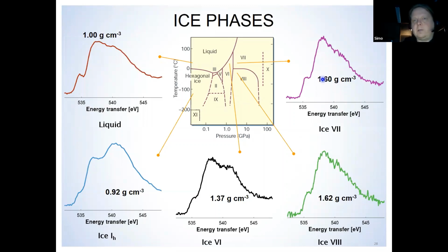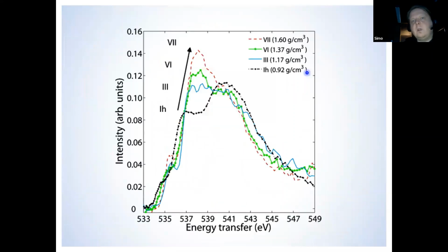They look like this. They have basically lost this post-edge feature, which is this hump that is strong in the Ice Ih edge. And now, using this, we are trying to understand what these spectral features mean. In this case, this pre-edge that is increasing in ice 7 and ice 8 cannot be due to distortions to the hydrogen bond network, because we know that there are none in these ice phases.